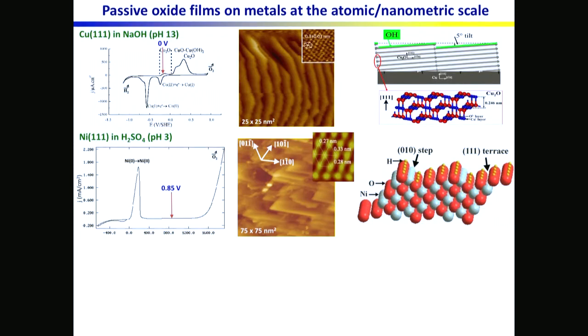So now, this was just about dissolution in the passive state. Now, if I come back to this film, so again, it's crystalline. It's highly crystalline, actually. It's in the quasi-epitaxy with the substrate, but only quasi-epitaxy, because, again, when you see that there is a tilt angle between the substrate and the oxide. And we could measure the tilt angle by looking at these images. And this is shown here.